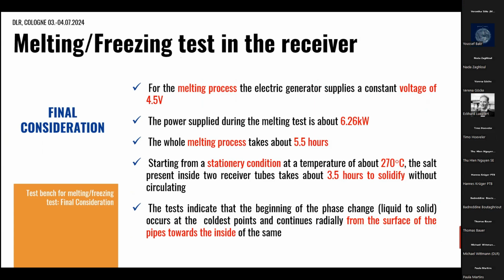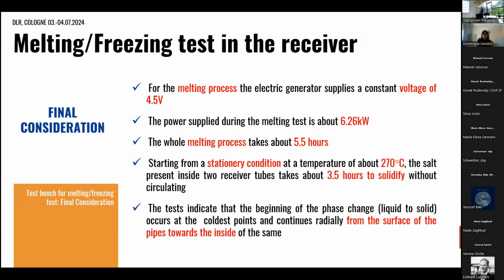Instead, concerning the freezing, the salt inside the two receivers takes about 3.5 hours to solidify without salt circulating. And this test indicates that the beginning of the phase change, both melting and freezing, occurs at the coldest points and continues radially from the external surface towards the inside of the tube.